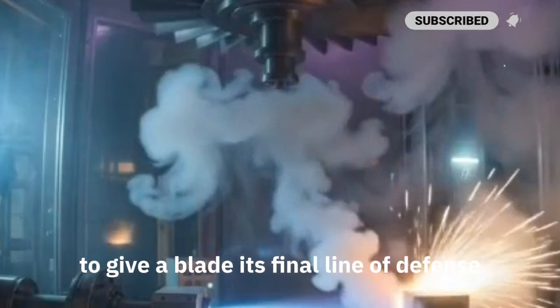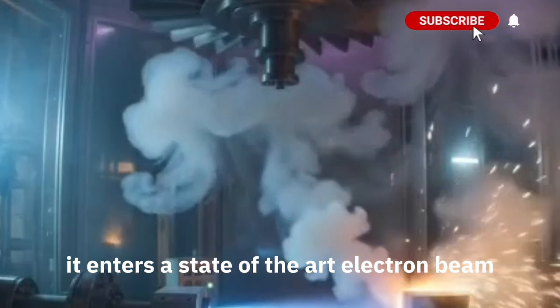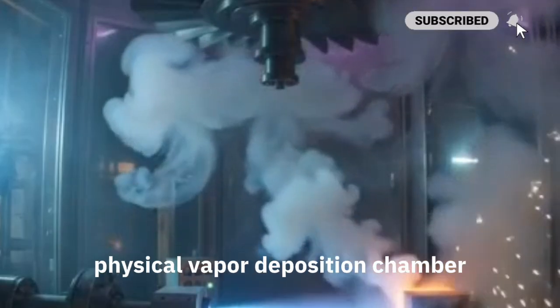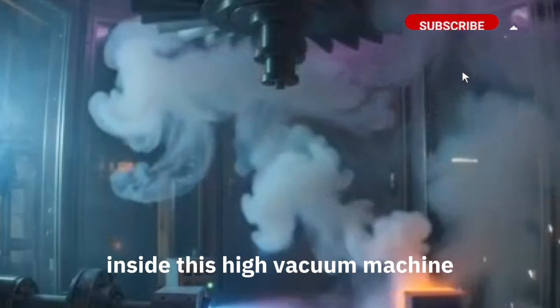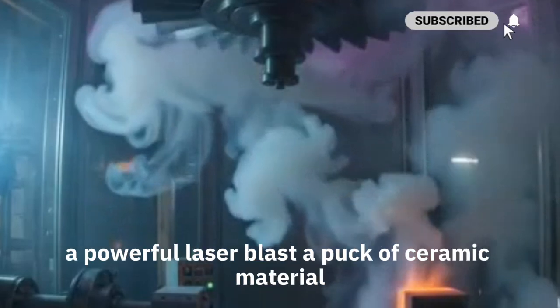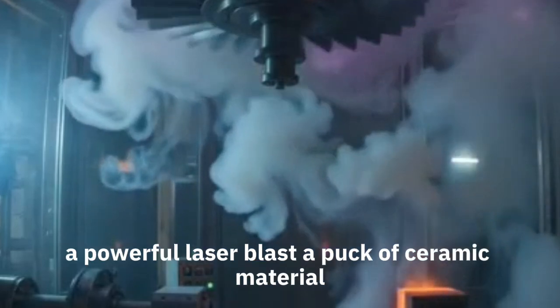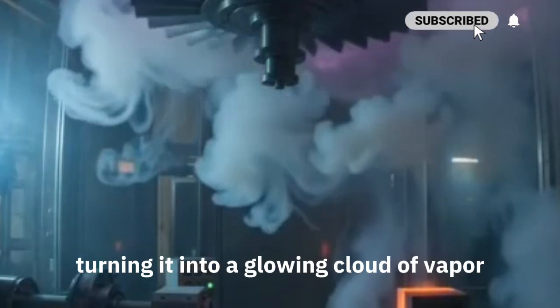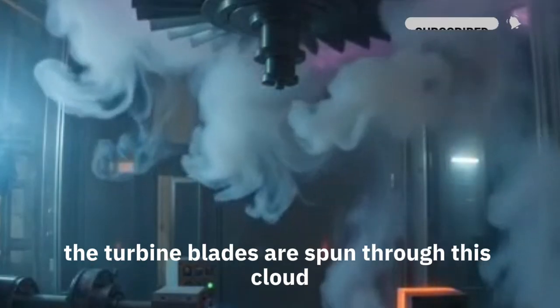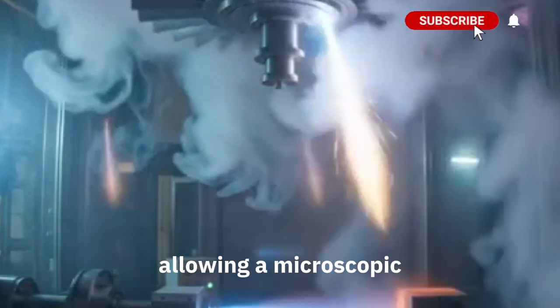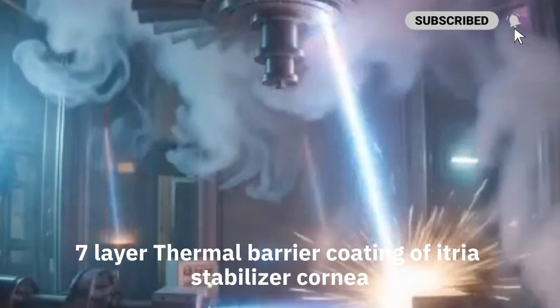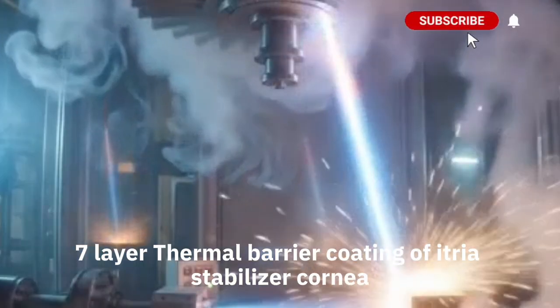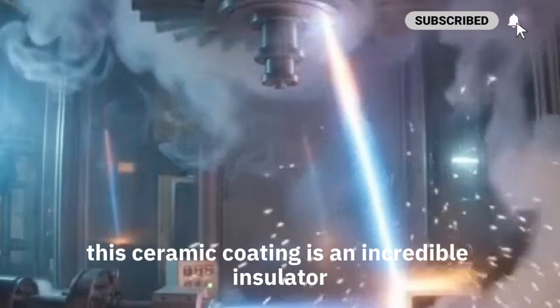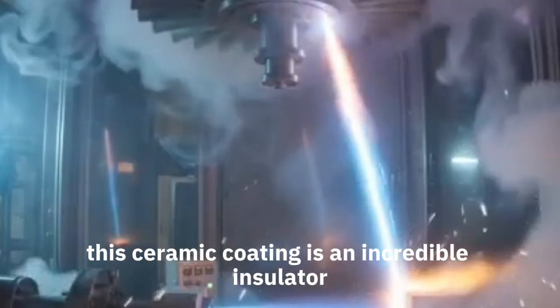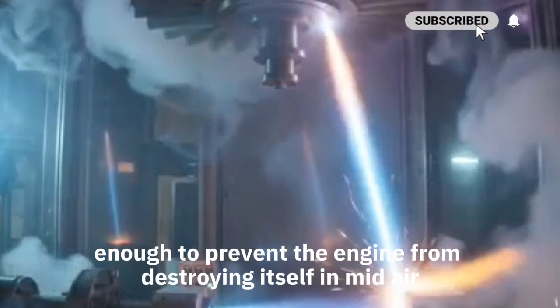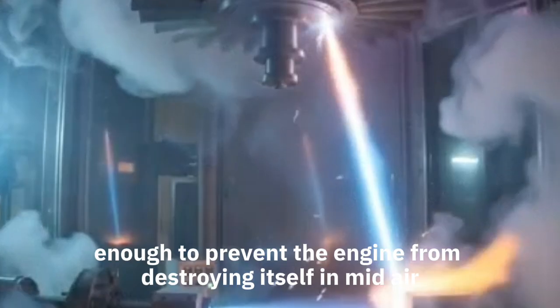To give the blade its final line of defense, it enters a state-of-the-art electron beam physical vapor deposition chamber. Inside this high-vacuum machine, a powerful laser blasts a puck of ceramic material, turning it into a glowing cloud of vapor. The turbine blades are spun through this cloud, allowing a microscopic, 7-layer thermal barrier coating of yttria-stabilized zirconia to settle onto the surface. This ceramic coating is an incredible insulator, ensuring the metal stays cool enough to prevent the engine from destroying itself in midair.